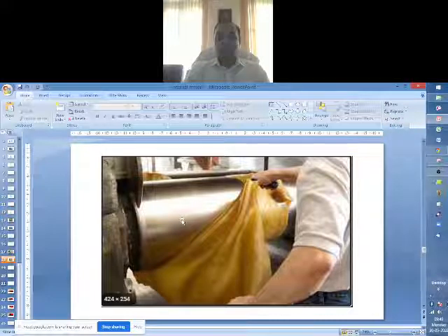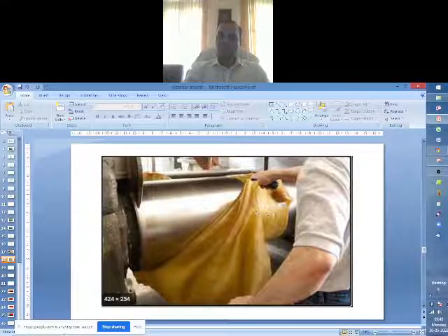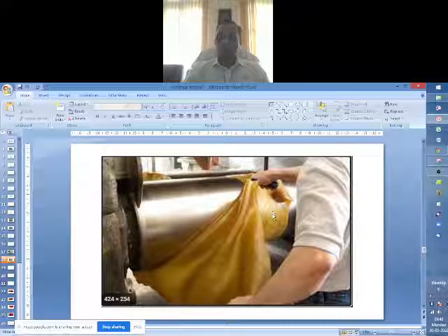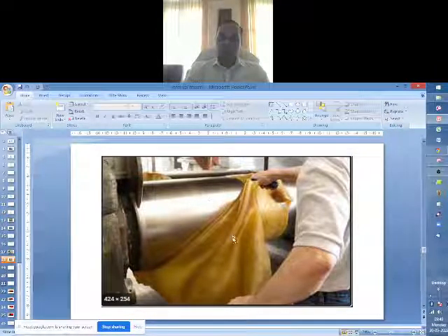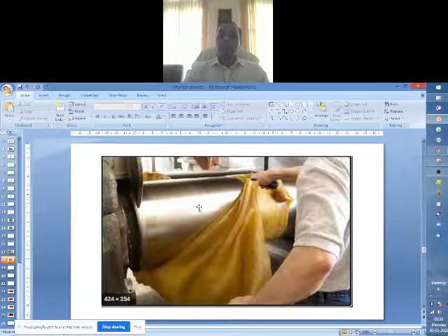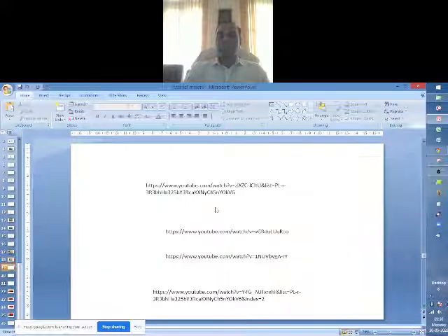The fundamental rule is, when the band is not uniform and the roll is visible through the cracks or breaks on the band, then you don't put in your ingredients. Because in that case, the ingredients will go into the space between the roll and the band, and then that will not be mixed easily. Okay, so we have a few videos here to see how it works.